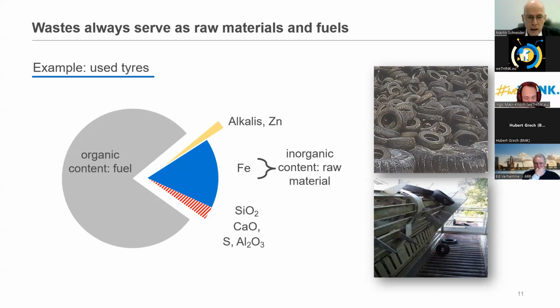And we need not only the calcium oxides that I've been talking about, and the silica oxide from the clays, but we also need other elements from clay minerals like aluminum oxide. But we also need iron in order to form sufficient, as we call it, melting phase in the kiln to allow this transition to happen from limestone to clinker.